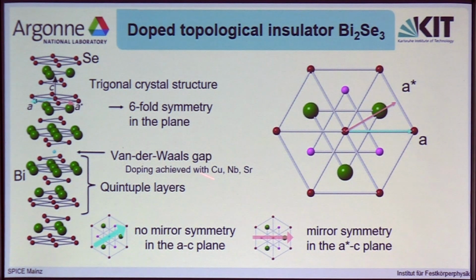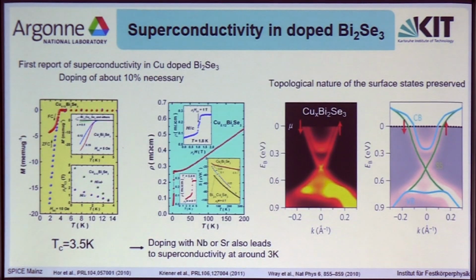Now, as I said, we can dope the system, and it was discovered for the first time with copper doping that if you do about 10% copper doping in bismuth selenide, the system becomes superconducting. You can see the very first measurements of magnetization and resistivity here. The superconducting transition temperature is about 3 Kelvin. And also very nicely done shortly afterwards were ARPES data, where we see that with the doping, we of course induce charge carriers. We thus raise the Fermi level from this band gap into the conduction bands, having the charge carriers now available for superconductivity. But luckily, we do preserve the spin-momentum locked surface states that we have from the topological insulator. So we do preserve the topological nature of our material.